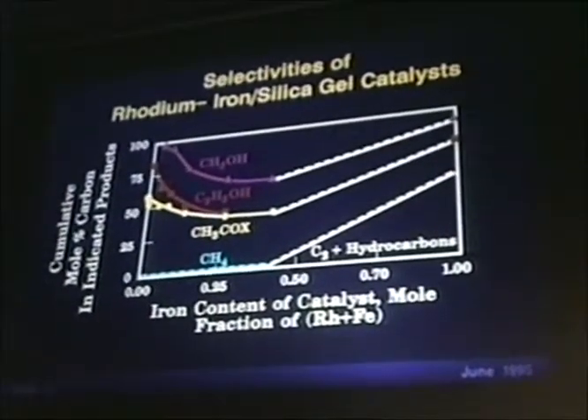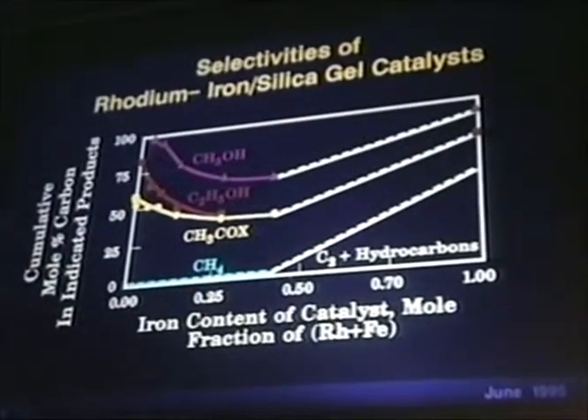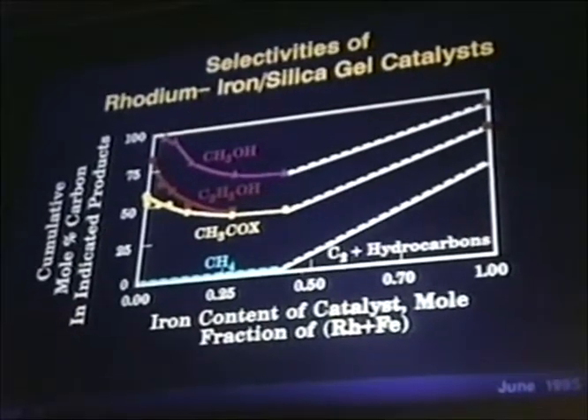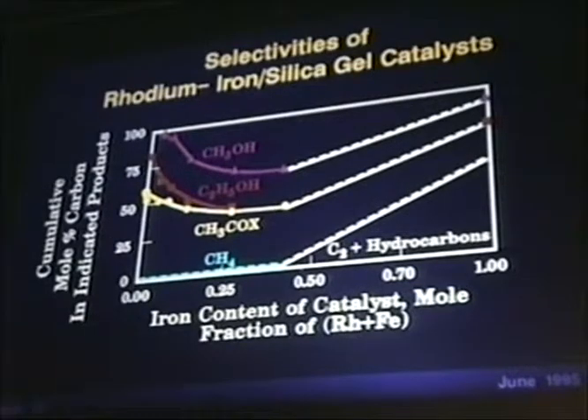I plotted iron content in mole fraction of the total rhodium plus iron, and the cumulative product efficiencies in mole percent on the y-axis. As you can see on the extreme left, where there is zero iron, and by the way, we cleaned up the system entirely in order to get that analysis, and I want to share that is another very significant role of surface science. We found that the starting silica gel always had impurities. That was calcium, iron, and a few other alkali metals on and off. Hence, we followed an oxalic acid washing procedure to be sure that we had a pure rhodium silica gel system, and that's where we got the performance and selectivities for zero iron containing catalysts.